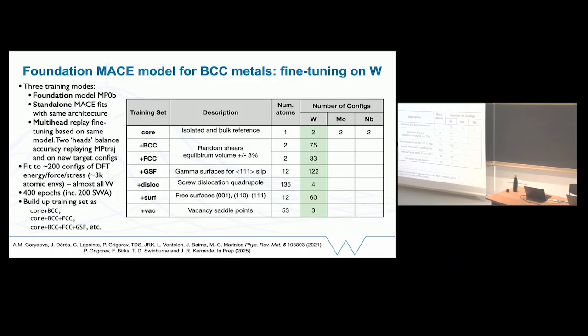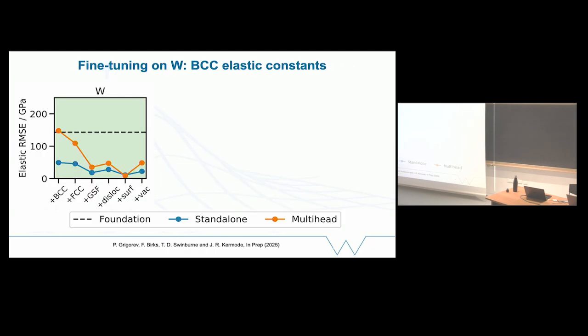And I built the data set up bit by bit to see how things improved as I added these different configurations. Okay, so the first thing was to look at elastic properties. That's what I was interested in getting right for my target applications. If you fit the model on its own, of course you can match elastic constants on tungsten using only a few databases. In fact, you can do it a bit better than you can using this multi-head approach.